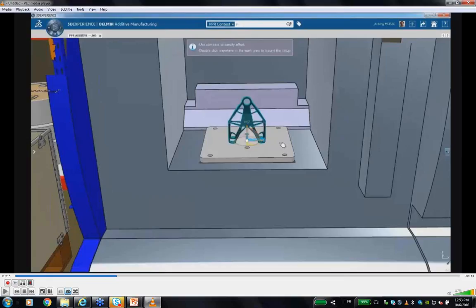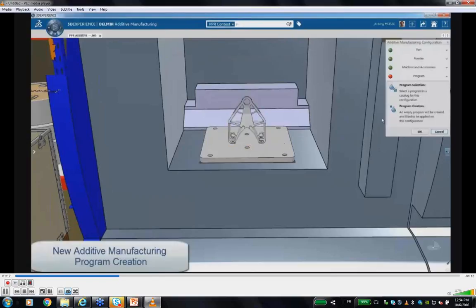Today, as an average, it is considered that 50% of the price and the time spent to get a part from a 3D printing machine is coming from the finishing. Because removal of those supports is extremely painful, especially if it's a very hard material such as titanium, Inconel, or stainless steel. Okay, it's a little bit easier on aluminum, but even in aluminum it's not easy. So let's optimize the position of the part on the tray to minimize the support and the height.